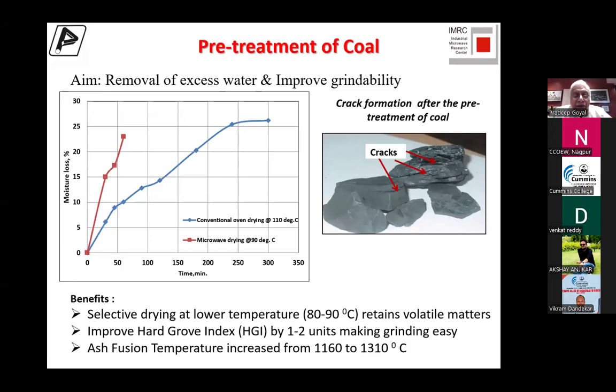And the third benefit we got was that the ash fusion temperature increased from 1160 to 1310, which is extremely crucial for a power plant. When you heat coal in a power plant, the ash that comes out of the coal goes and chokes up your tubes. But if the ash fusion temperature increases, then these ashes will not stay in the tubes, they will go out. So the tubes will last longer. That is another big advantage that came, which we were not really expecting. That was an unusual thing that we realized.